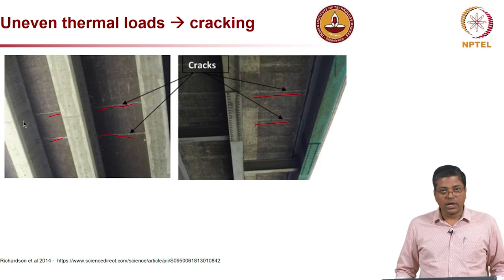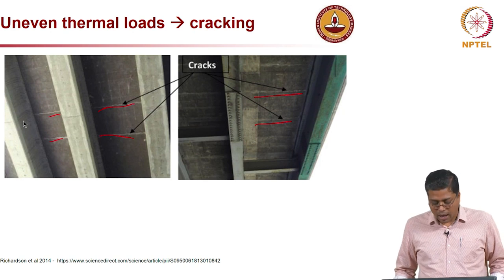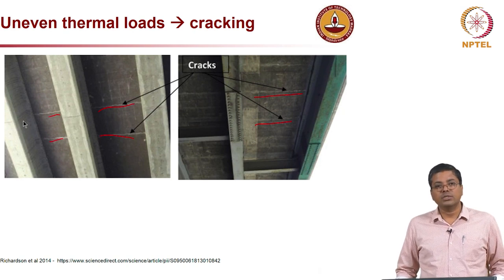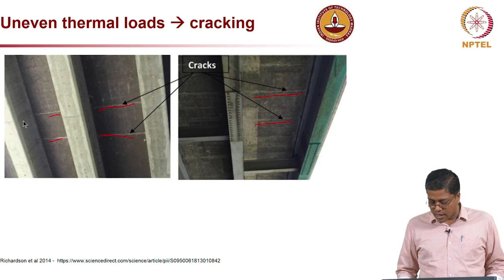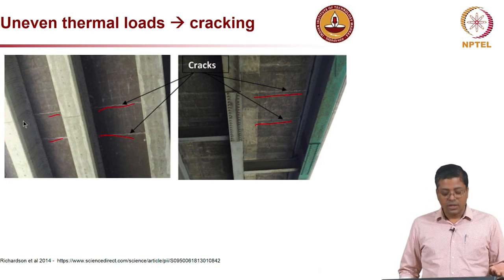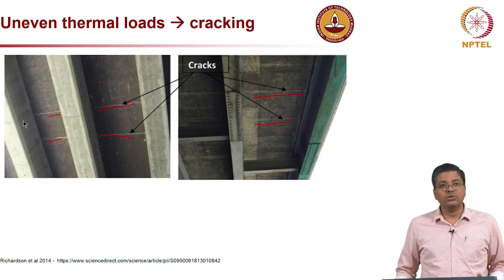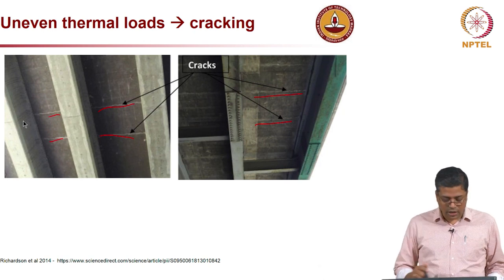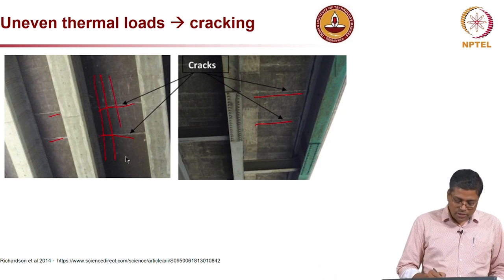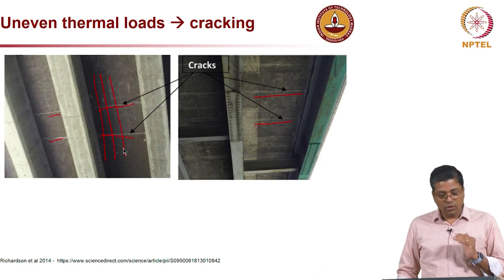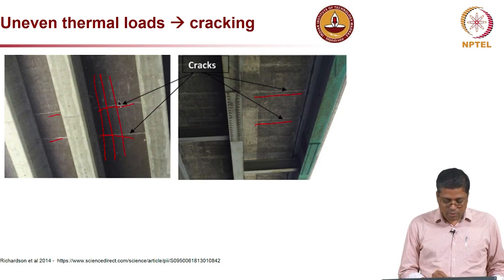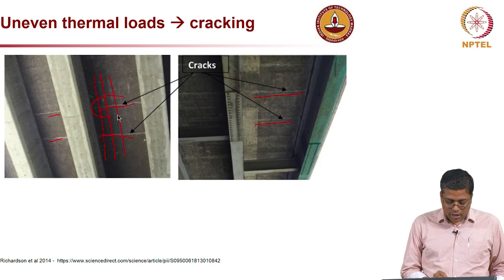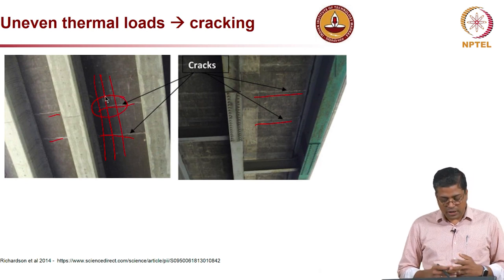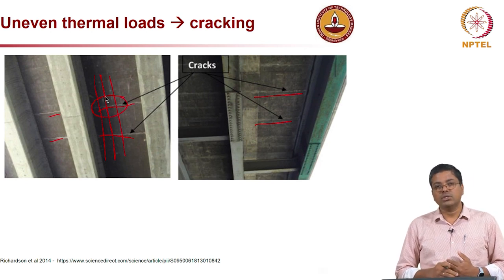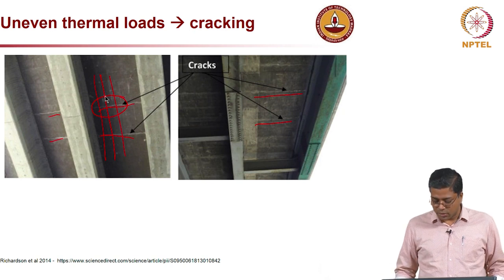You can see some cracks. So, these kinds of damage mechanisms happen especially on large structures, and which could later induce problems. Imagine in this particular bridge, you have a crack there, and there is reinforcement which goes like this in these cracks. And when you have a crack, definitely that rebar is going to experience localized corrosion right here. So, definitely these kinds of damages will lead to long term performance issues.